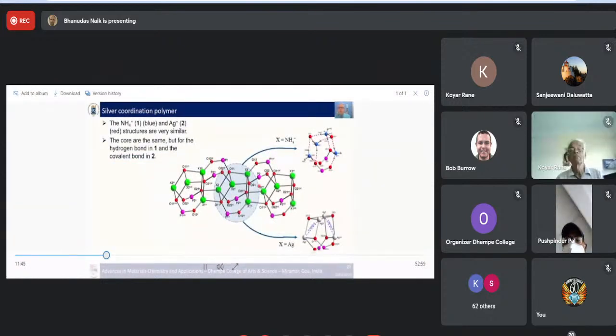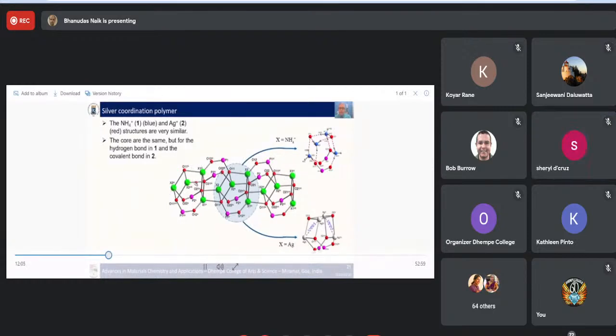You can see in the center of this compound, you basically have an oxygen bridge center here, and these phosphonate groups are here. They join with the organic linker to another chain of these oxygen-bridged silver centers. And you can see that the centers of these are almost the same. This is the ammonium center. The center here, if you look at it, you can see that it's a tetrahedral center. You have 4 oxygen atoms around that on each side, and you can see that here as well. The hydrogen bonding.